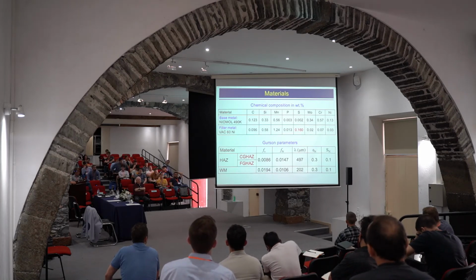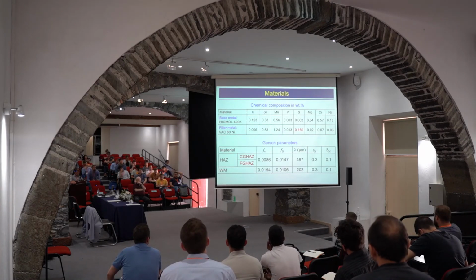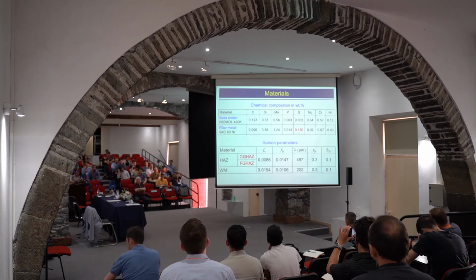You can see basic data about chemical composition. What is here marked in red is strange data that we obtained from the producer, who claimed that there is sulfur as high as 0.16, which is probably wrong. That's still to be checked. It probably should be 0.016, but even that is a relatively high value. You can see also that phosphorus is relatively high in pure metal, and that is relevant to interpret results that we obtained at the end of this testing.